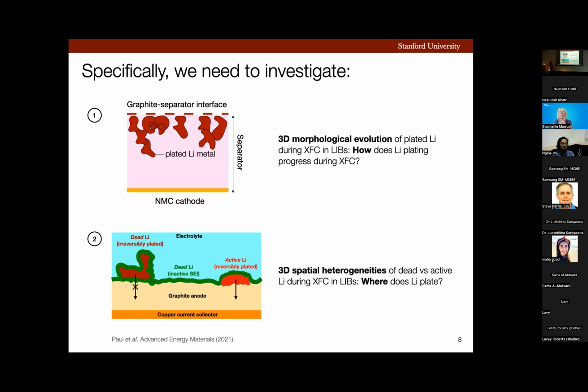However, dead lithium is the one that is irreversibly plated. As you can see from the direction of this arrow, this lithium has no electronic pathway open to it to intercalate into graphite and go back to the cathode during the discharge process. And dead lithium is the one that is associated with battery capacity fade during fast charging. Therefore, understanding the 3D morphological behavior and heterogeneities of dead lithium and differentiating them from those of active lithium is essential to developing an improved understanding of how lithium plating causes battery failure during fast charging.